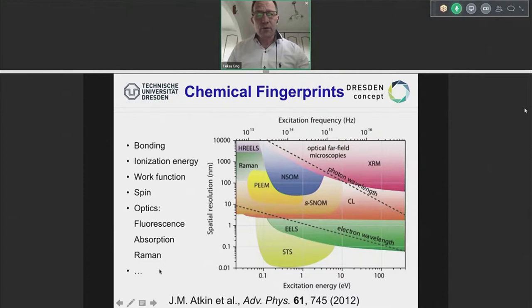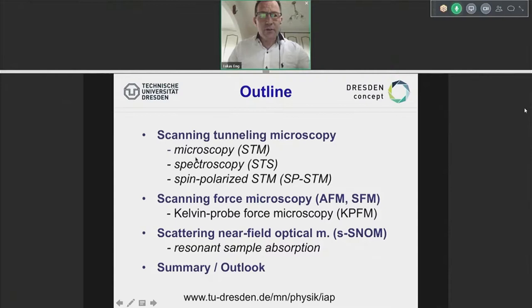So let's see where we are on this kind of scale by using the scanning probes. And that's what I want to discuss with this lecture here. I would start and show you that even when you do microscopy in STM, for instance, you already see only because the chemistry is correct, because we have the right density of states. I want to continue with STS, tunneling spectroscopy, and also spin polarized STM, but then also break the ice for something which I think is a very strong method to elaborate, which is Kelvin probe force microscopy that gives you direct access to work functions, which is a reflection of the local chemistry of systems. And finally, finish with resonant sample absorption in an SNOM system, which we have also done in collaboration, just as an example, with these guys here from Freiberg with the Helmholtz Institution. So I will show some results there.